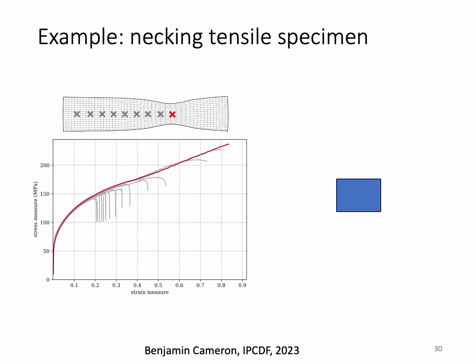You can also do this for elements outside the neck, and you can see that they elastically unload. And this square element just shows the strain at which the deformation was homogeneous, and you can apply classical methods to calculate the stress-strain relationship. But now we can calculate the stress-strain relationship up to this deformation, and these are drawn to scale for an originally square element.